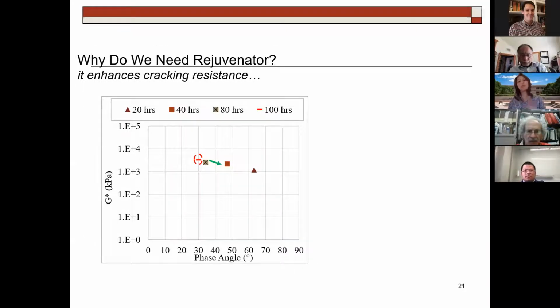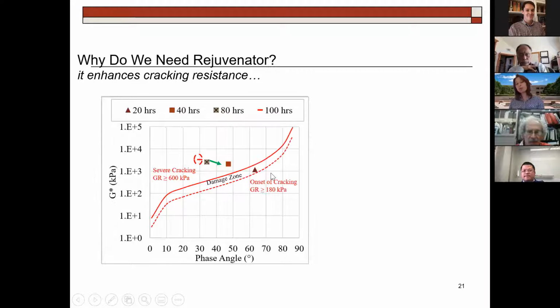Many of you know this, but even if you don't, as we move toward the left in this curve, left and up, it's getting worse and worse. So remember, left and up, it's getting worse. And you can see from the 20-hour aged material to 100 hours, we're all the way up here. Which one of these is more prone to crack? We have this threshold. If the dots are within the threshold or below this dash line, that's good. As it gets above this, severe cracking happens. Here, onset of the cracking. So we want to be as low and to the right as possible in this curve, at least.